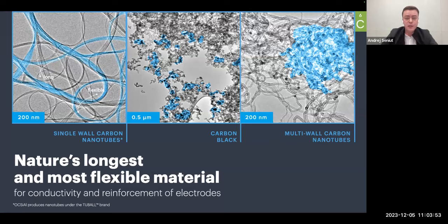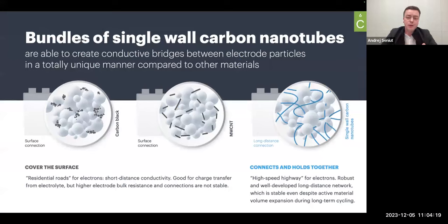But now, to prove the statement, please look at these TEM images of different conductive materials which can be used as conductive and reinforcing additives in lithium-ion batteries. As you can see on the left side, the single-wall carbon nanotubes, and only by looking at the images, you can see that this material is substantially longer and more flexible in comparison with carbon black and multiwall carbon nanotubes. So this difference in morphology of single-wall carbon nanotubes actually determines the difference in performance of our material in various